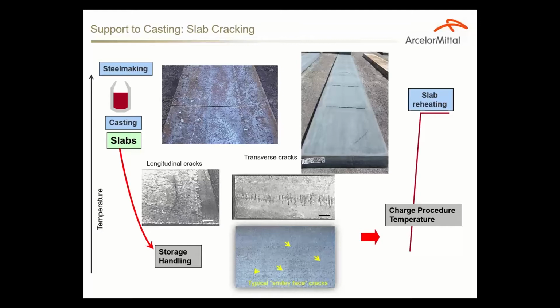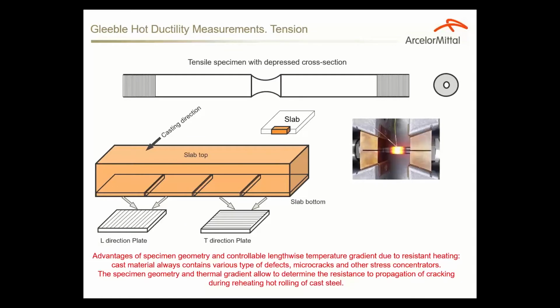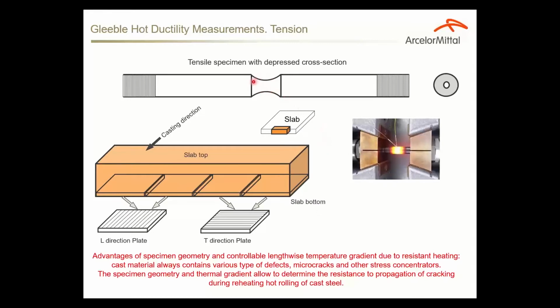to do this, we perform the hot ductility measurements that imply heating tensile specimens to a very high temperature, soaking, and pulling in tension at different temperatures. This scheme shows you how we machine the samples from this slab, and on top you can see the geometry of the sample. We use round cylindrical specimens with a depressed cross-section in the center, just because Gleeble mainly uses direct resistance heating, so we have to make sure that the specimen fractures at the point where a thermocouple is welded.